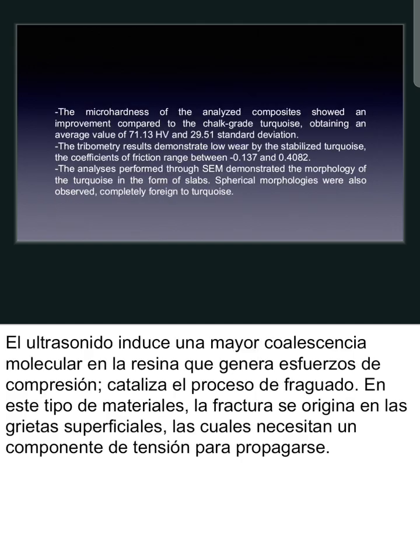The microhardness of the analyzed composites shows an improvement compared to the chalk-grade turquoises, obtaining an average value of 71.13 microhardness and 29.51 standard deviation. The tribometry result demonstrates low wear by stabilized turquoise. The coefficient of friction ranges between minus 0.137 and 0.4082. The analysis performed through SEM demonstrated the morphology of the turquoise in the form of slabs. Spherical morphologies were also observed, completely foreign to turquoise.